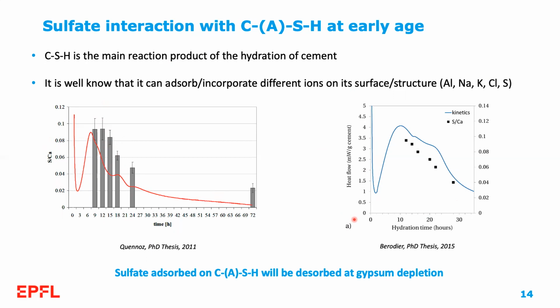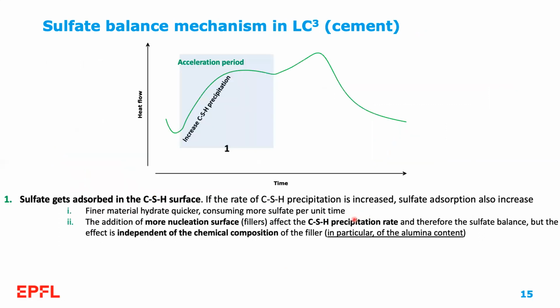This allows us to formulate our mechanism of sulfate balance of LC3 and in general of any cementitious material. We can divide this in two stages. During the first stage, sulfate gets adsorbed in C-S-H surface. And it's very important here to realize that if the rate of CSH precipitation is increased, sulfate adsorption will also increase. In this regard, finer material, as finer clinker for example, hydrates quicker, consuming more sulfate per unit time. So this cement will have higher sulfate demand.